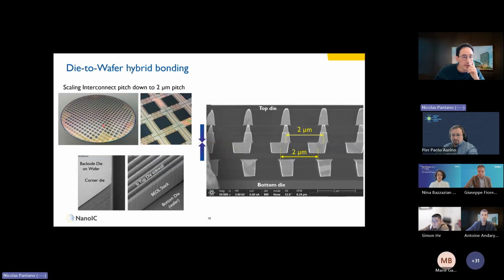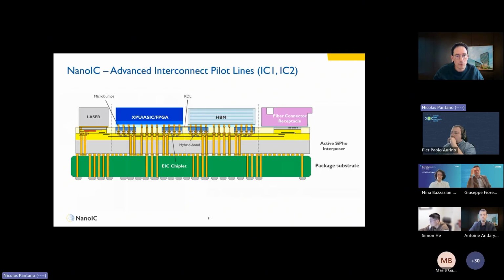This is an example of an illustration of what I said just before, where we have several die. These black dots are chips that are hybrid bonded on the wafer. And you can see here, unless I tell you that the interface is here in the middle, you would not even know that the chips are actually bonded on this layer. And you see that you have very clean connection between the top and bottom, and a 2 micron pitch. So this is for hybrid bonding. Hybrid bonding is very good. This is excellent for 3D applications.